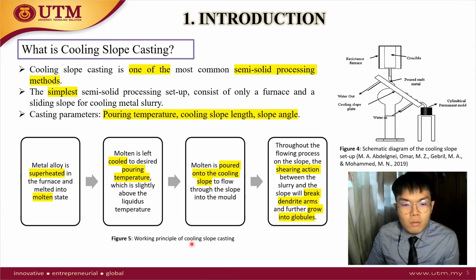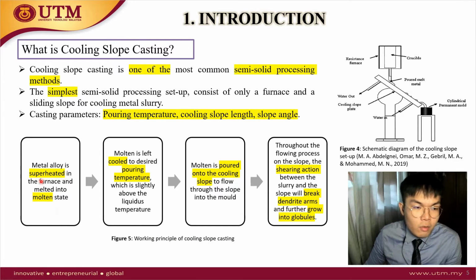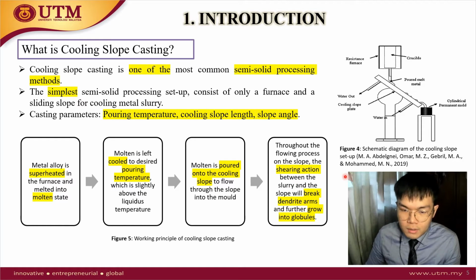The working principle of cooling slope casting starts with the metal alloy being superheated in the furnace and melted into molten state, and the molten metal is left to cool to the desired pouring temperature, which is slightly above the liquidus temperature. The molten metal is then poured onto the cooling slope to flow through the slope into the mold. Throughout the flowing process on the slope, the shearing action between the slurry and the slope will break dendrite arms from the mother dendrite, which further grow into globules.